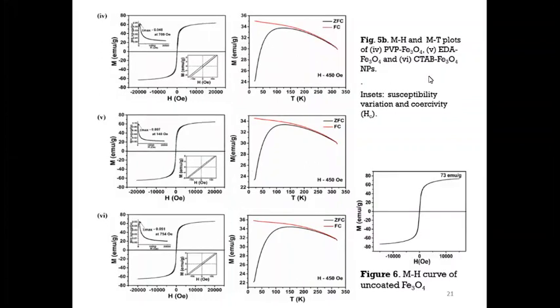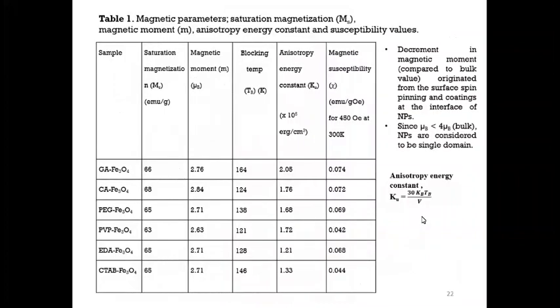So similar behavior has been found in the other coatings too. And this is the magnetic curve for the bare nanomaterials without coating. Without coating, of course, there is agglomeration, but still the magnetization is very high, because the surface coating is less than 10%, around 5 to 10%. Coating layers like glutamic acid or citric acid are magnetic dead layers. These are diamagnetic materials, so they will not contribute to the magnetization of the iron oxides, and hence the coated samples always possess lower magnetization than the bare one without coating.